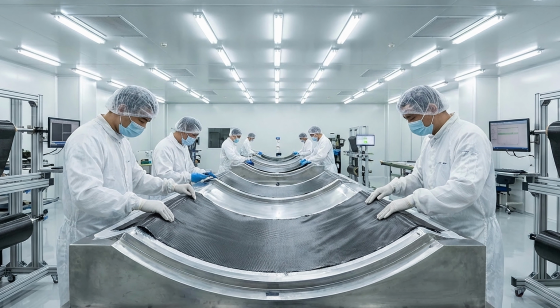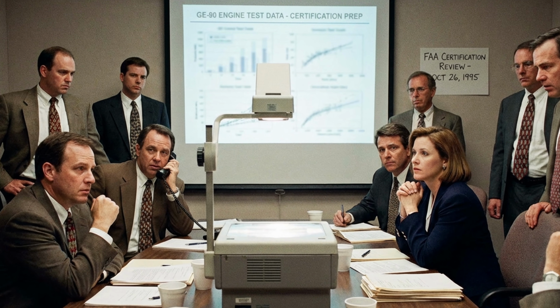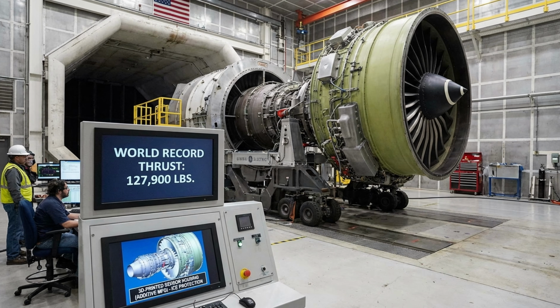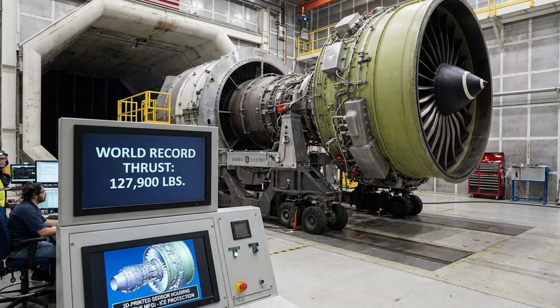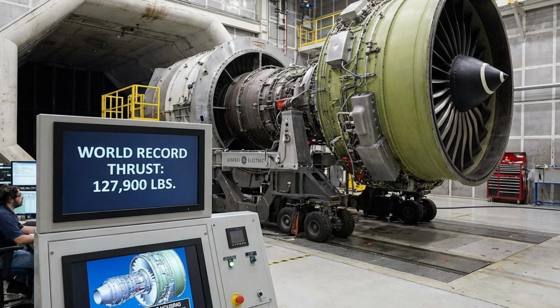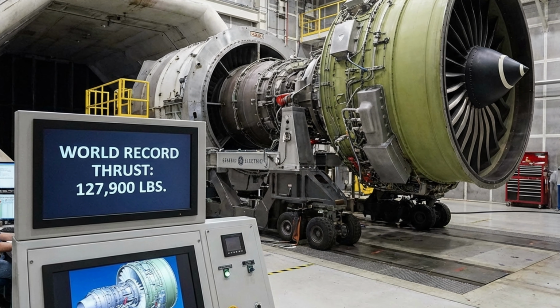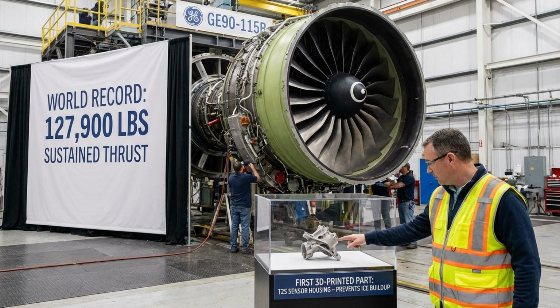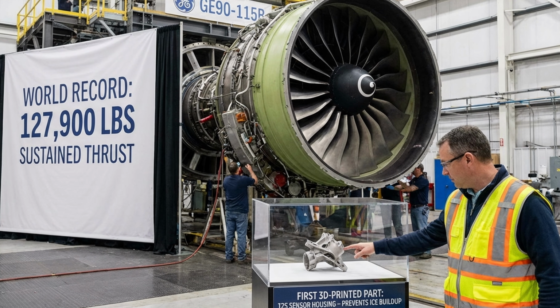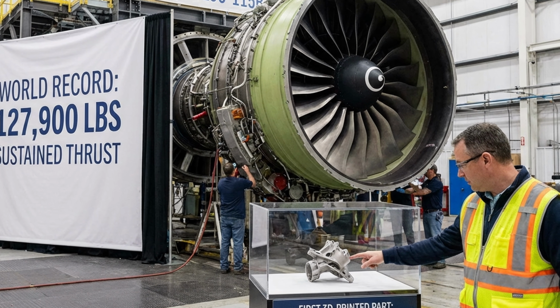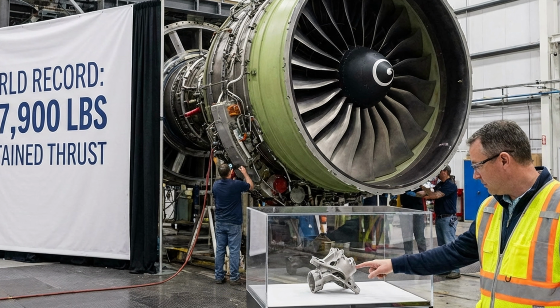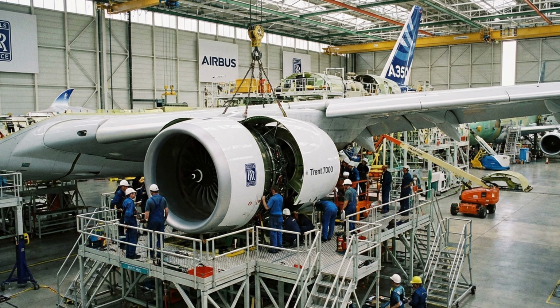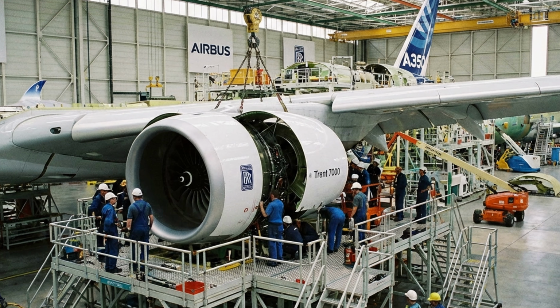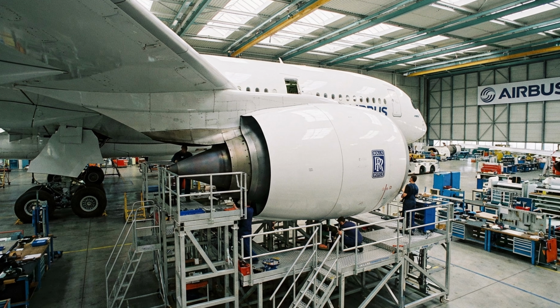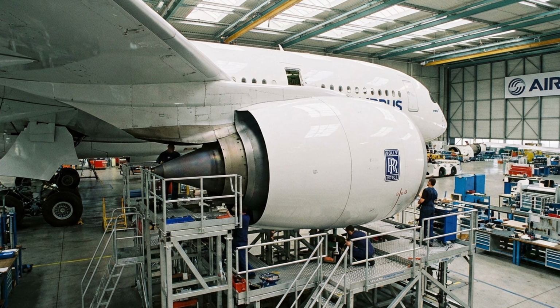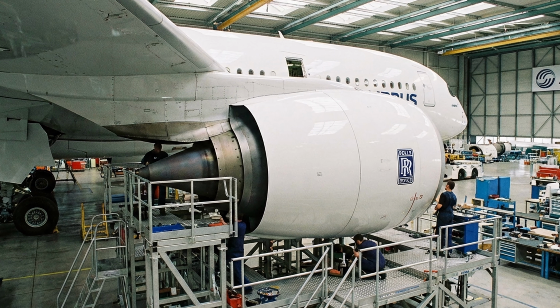large fan diameters. Certified in 1995 in a tense room of Federal Aviation officials, the GE90 later set a world record by producing 127,900 pounds of sustained thrust, and it famously became the first commercial jet engine to utilize a 3D printed component, an additive manufacturing breakthrough that solved critical ice buildup issues on internal sensors. Similar paradigm shifts occurred across the Atlantic, with the Rolls-Royce Trent engine family routinely achieving bypass ratios of 10-to-1, making them 70% more fuel efficient than early turbofans like the Conway.